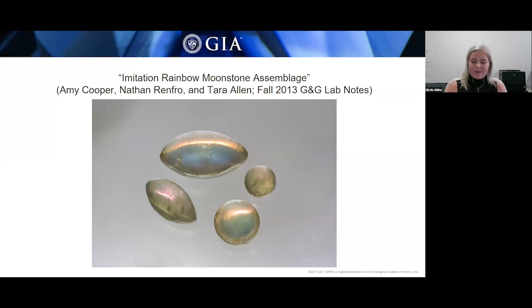While examining that quartz layer, it was observed that it was coated with an iridescent coating, kind of like one might see on an opal or quartz. The plastic coating on the whole assemblage was easy to identify due to it having numerous contained gas bubbles. So to summarize, we have this piece of natural rock crystal quartz with an iridescent coating, and then you have the cemented piece of fibrous gypsum on top of it. And then the whole assemblage was just coated in plastic. These are the type of stones that keep us gemologists right on our toes.